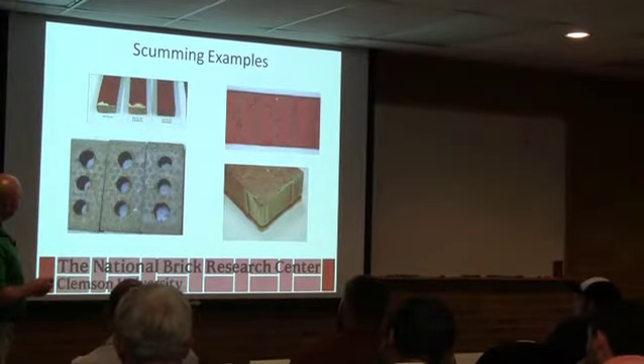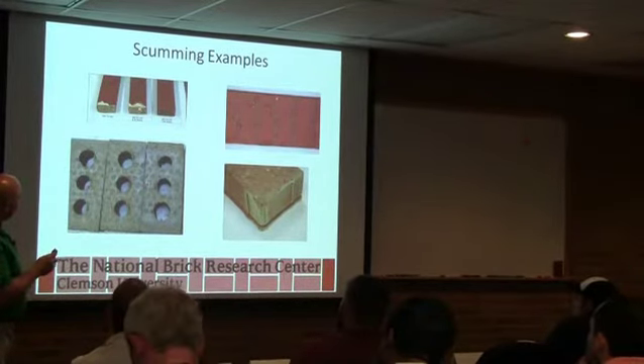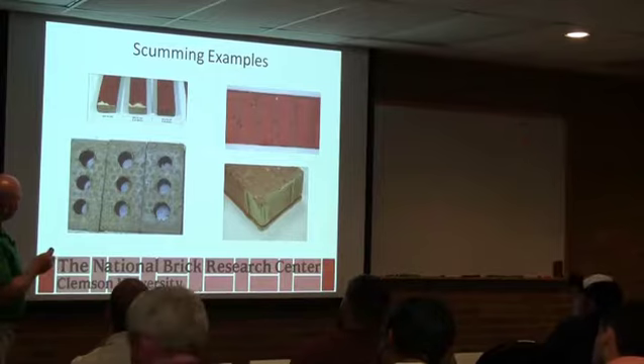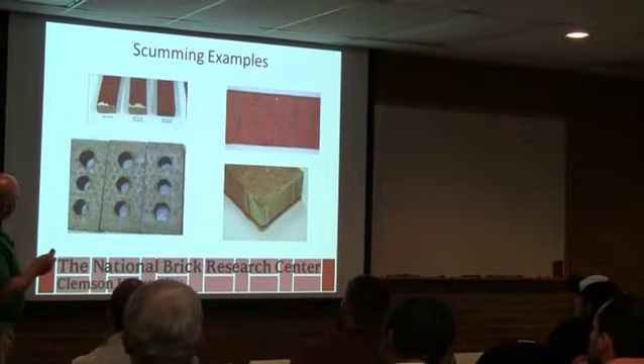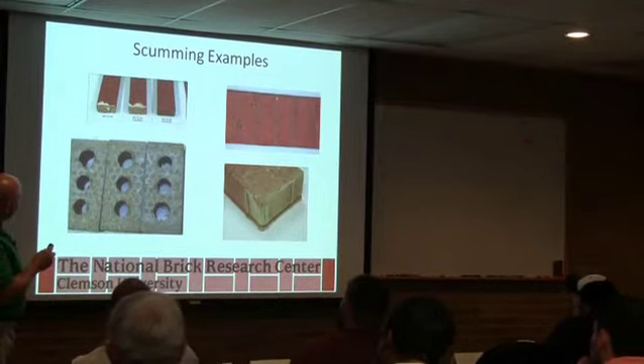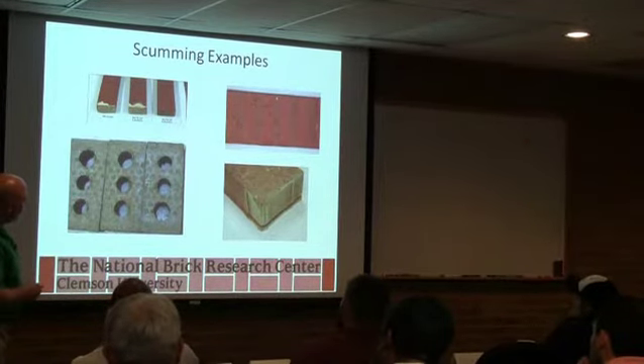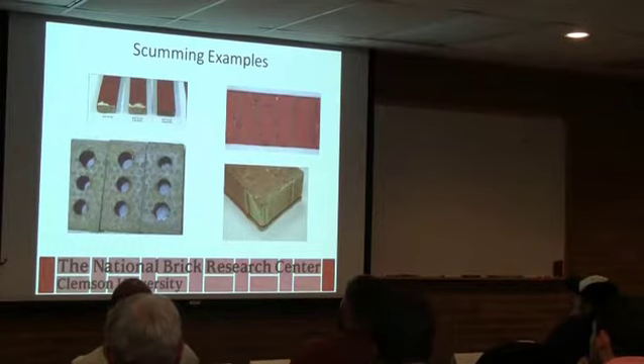Here's some examples of scumming. Again, that's pretty permanent after it's done. And here they were trying to use barium carbonate to eliminate it. So that's no barium carbonate, 0.2%, 0.4, starting to get it under control. A lot of times you see these stripes where the brick on top was sitting there. You always look for scumming. You can see a pattern.